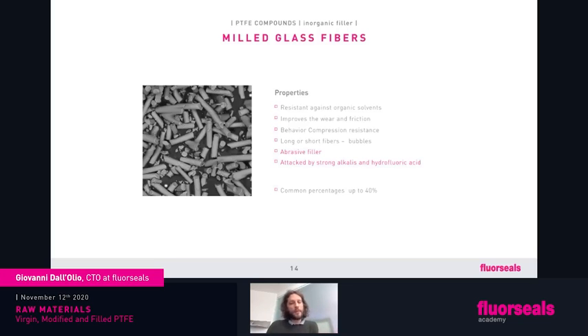So when we do have a dynamic application, it's almost anytime better to use a PTFE compound. There are some cases where virgin can also be used, but 90% of dynamic applications use PTFE compounds because the filler inside PTFE will improve the wear resistance. So going back to glass, it improves the wear, but it affects the friction too. Improves is maybe the wrong word. The friction will be higher, and it's not always a good thing, but it's not a major difference. It's a bit higher compared to virgin PTFE friction.